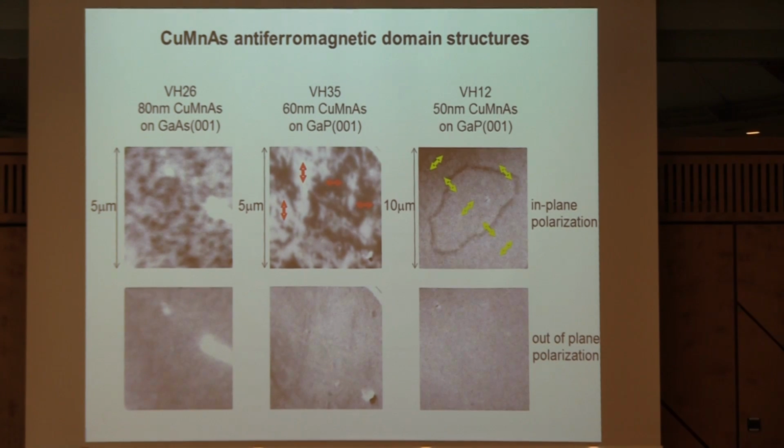The reason I don't want to draw any broad conclusions from them is that every one of these layers so far has been grown for a specific reason, and that means things were done differently. In this case, this one had quite a large buffer layer for historical reasons. I don't know what difference that would have had, but also this layer was grown a little bit later and we had more accurate temperature control of the substrate. So although there is a clear difference between them all, I can't really associate it with something we're doing. I think it really requires a systematic study of the growth conditions. It's something we really want to master because this sample is extremely interesting to me now.